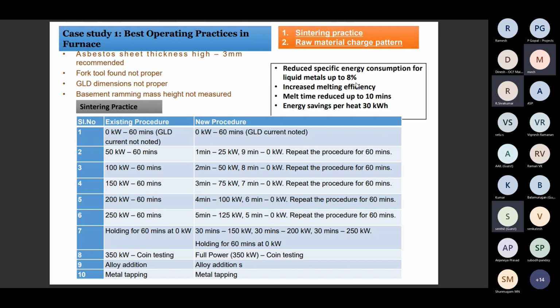The second step in the existing practice is 50 kilowatt for 60 minutes continuously in 1 hour, with 50 kilowatt maintained by the power capacity of the furnace. In the new practice, for 1 minute 25 kilowatt was given, and for 9 minutes it was 0 kilowatt. It is repeated for 60 minutes, that is, every 10 minutes, 1 minute at 25 kilowatt and 9 minutes at 0 kilowatt. So 6 cycles of 25 and 0 kilowatt were repeated.